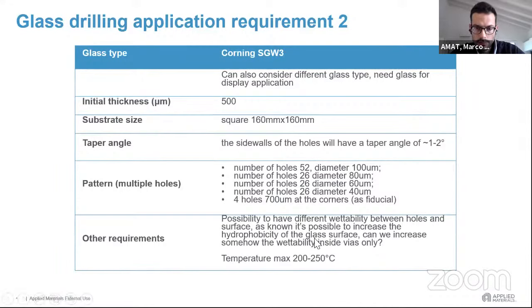If we could ideally increase the wettability inside the vias, this could be a big breakthrough for this application because we need to apply some materials inside these vias. And we have an additional requirement, which is also to be met or understood. The full substrate should not go higher than 200 degrees C because there are structures which have been pre-deposited that can withstand up to this temperature.